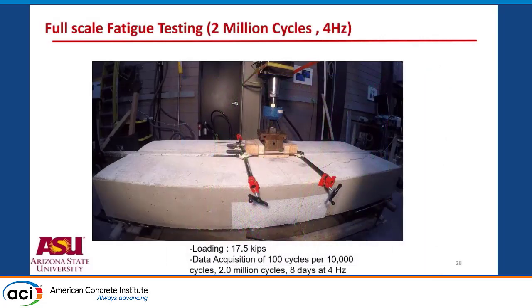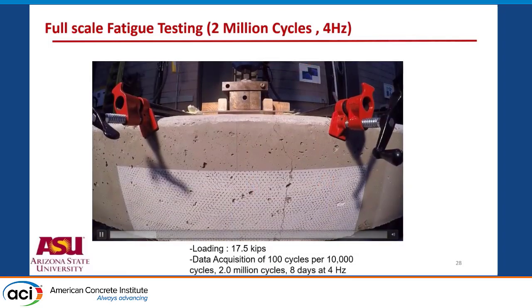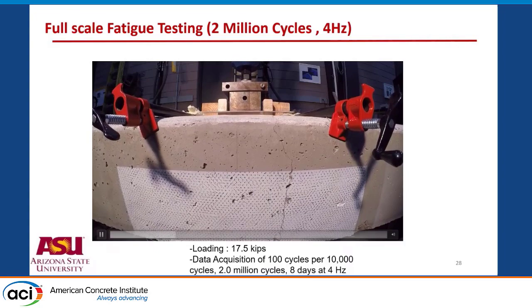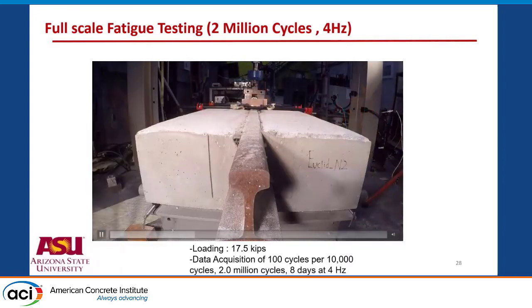So here, let's take a minute for a video. The fatigue test. We're running the fatigue tests at 4 hertz, 2 million cycles, and it takes about 8 days to run the test. This was done after you load the sample to full cracking. So first you load it to full cracking, and then subject it to the cyclic load.